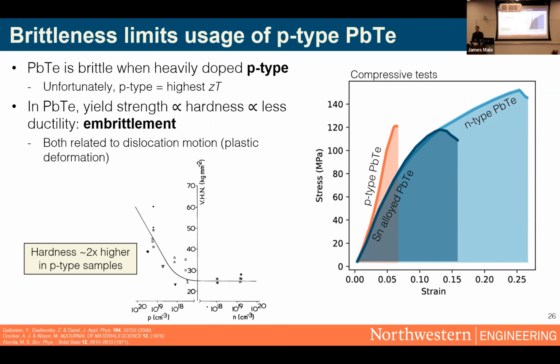So beyond qualitatively, what I mean when I say brittleness is essentially that N-type lead telluride can deform much more than P-type lead telluride. And in these stress-strain experiments, you can actually see that explicitly. Of course, P-type lead telluride can accommodate far less strain. These are the only 2 stress-strain experiments I'm aware of in the entirety of the lead telluride literature.